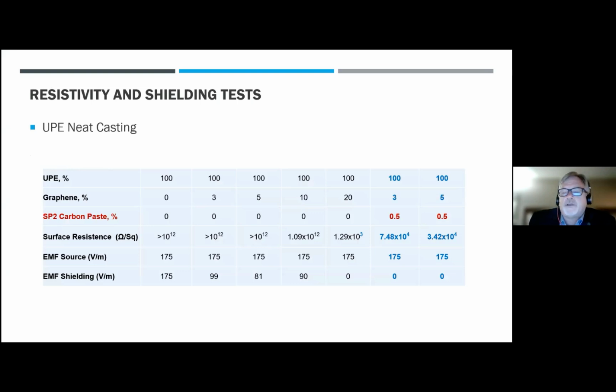All right, so I'll show a bit of our test results. We've done quite a bit of extensive testing in the labs for quite a long time, and this, of course, is utilizing a lot of our experienced scientists that have been involved in the industries for years. This shows an example of some resistivity and shielding on an unsaturated polyester neat casting. If you look at the first column, you could see there's no graphene or none of our additive in it, and you can see that the EMF source of 175, the shielding ends up being the same. There's in effect no shielding that is occurring in this neat casting.